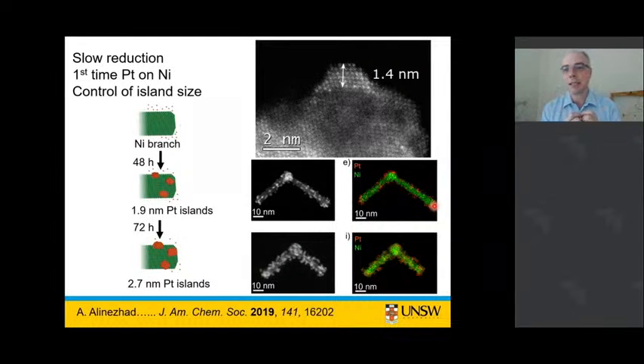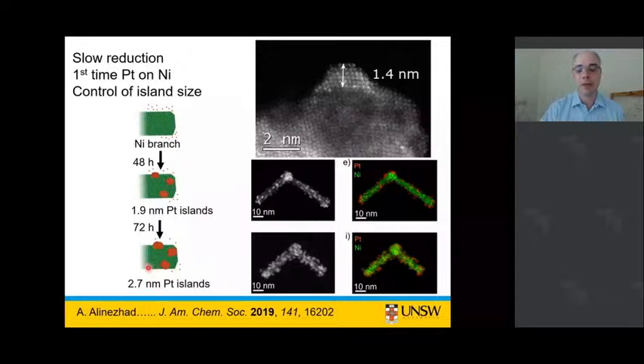It made these very small islands of platinum decorated directly onto the surface of the nickel. Because this decomposition is so slow, you have these platinum atoms whizzing around in your solution, and even though they don't really want to join onto nickel because of this large lattice mismatch, they really have nowhere else to go. So they do start sticking onto the surface and forming islands. If he waited a couple of days, he got about 2 nanometer islands, and if he waited a bit longer, 3 days, the islands could grow a bit larger as well.